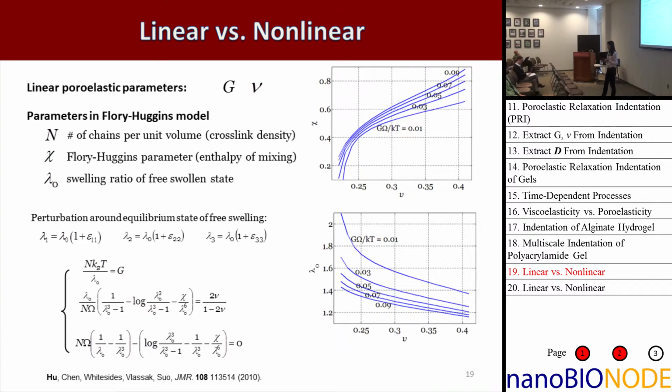And Flory-Huggins, sorry, I don't know where that slide is, but Flory, who got a Nobel Prize for developing this theory, said the free energy of the gel is a combination of stretching energy, stretching of the polymer chains, and mixing energy due to mixing of solvent molecules with polymer chains.